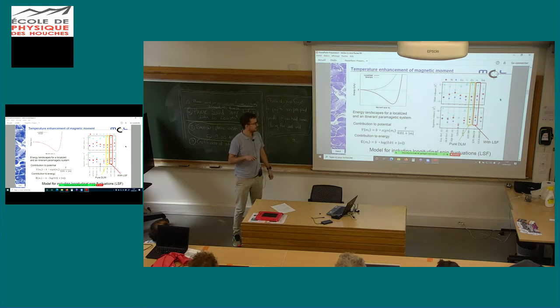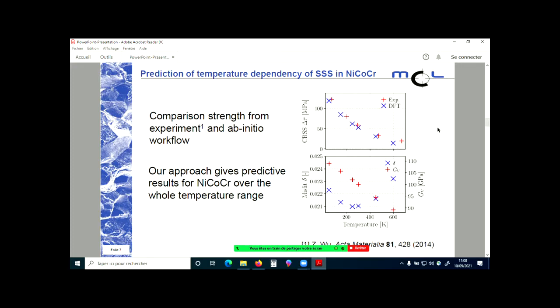And this can be incorporated into DFT by a phenomenological model that was proposed by Levente Vitos, I think, and András Ruban. It's called the phenomenological model for longitudinal spin fluctuation. And it really helps with the equilibrium volume and also with these derivatives. Yeah, so now let's go to the results.